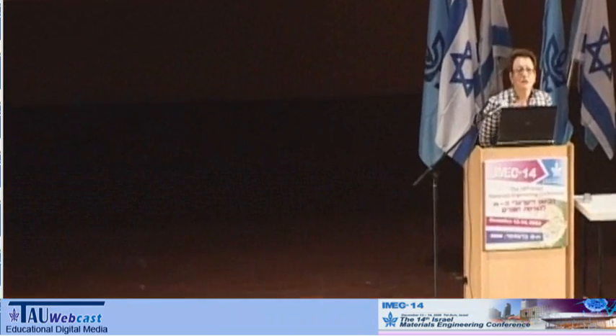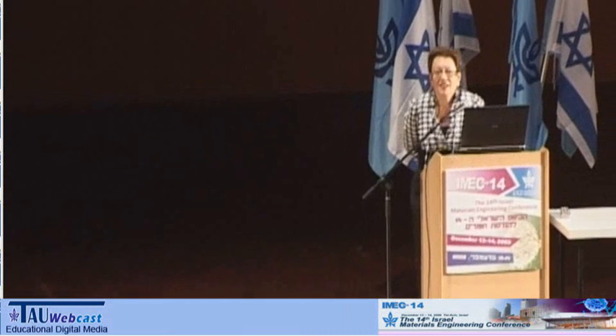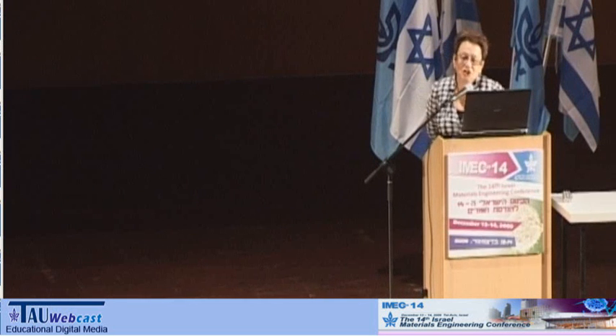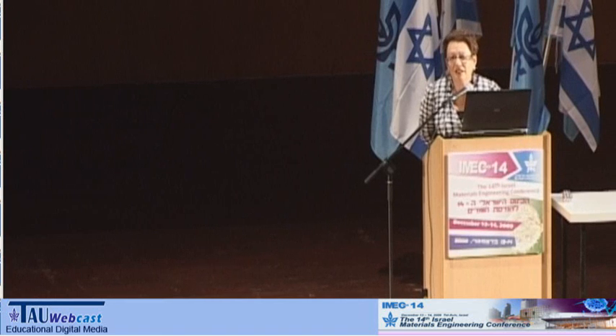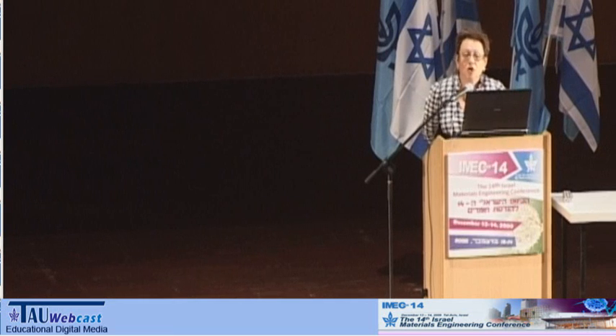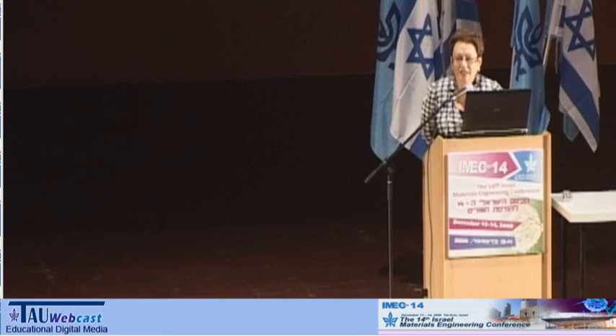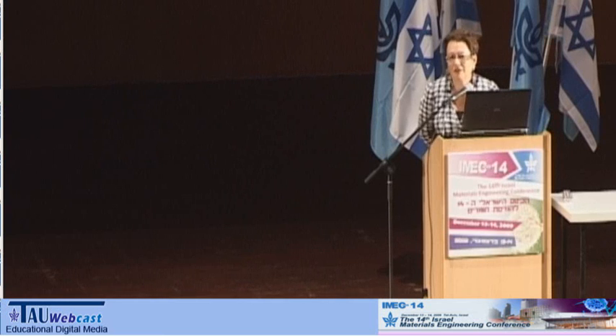Not only that I didn't show it, I didn't like to see it. The problem is that when you discharge the battery to the lower voltage region, you obtain a non-reversible lithium sulfide. And while we really achieved much better performance with modified electrolytes, it is still impossible to ensure complete reversibility of this material. Therefore, we charge it in the narrow voltage window. And this is actually our goal, to work in this window.